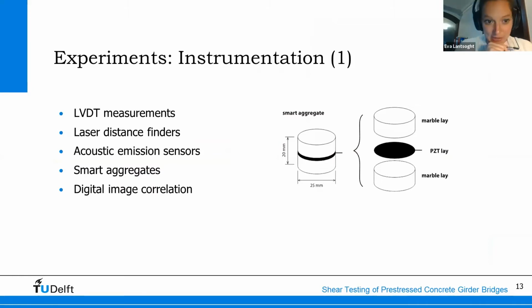In terms of instrumentation, we have applied a regular set of LVDT measurements to find our strains in a grid on the side. We've applied laser distance finders to find the deflections. We've used acoustic emission sensors to study the wave-based properties. We've applied as well smart aggregates and cast them into the specimen. And we've taken photographs to do an analysis using digital image correlation. So here you see an example of a smart aggregate. It's essentially a piezoelectric layer between 2 marble layers.